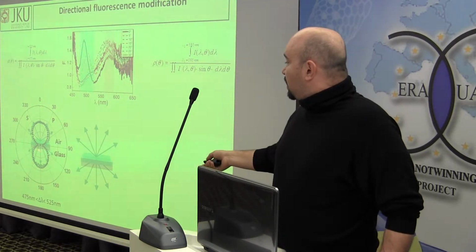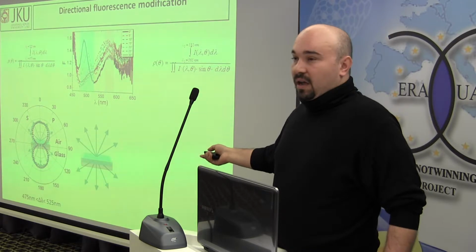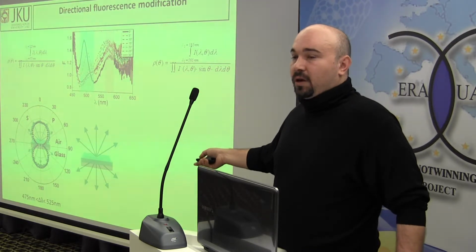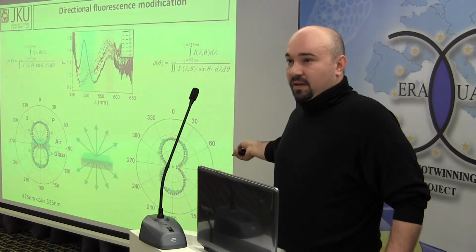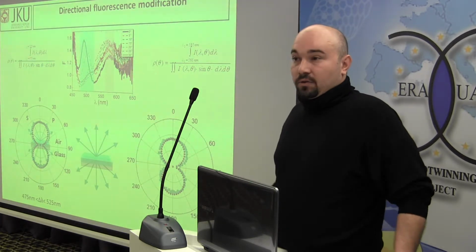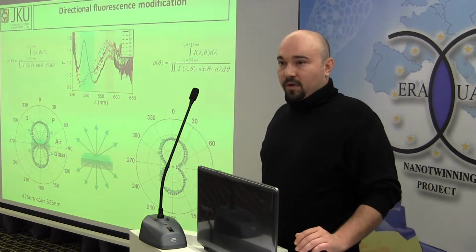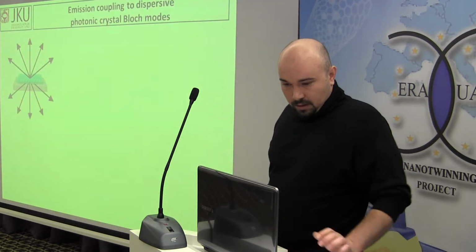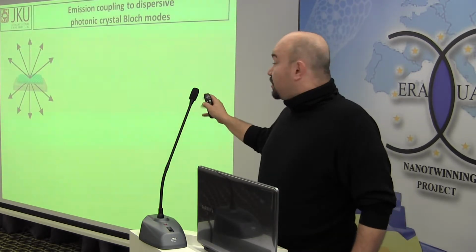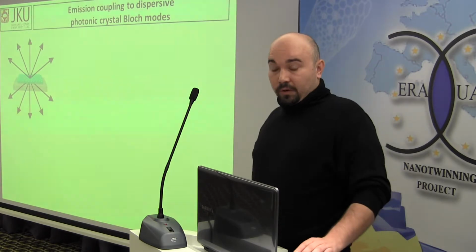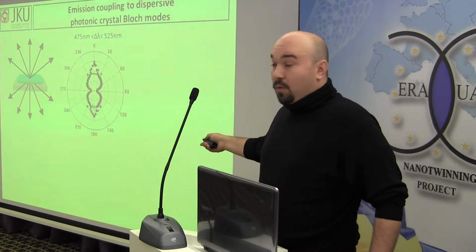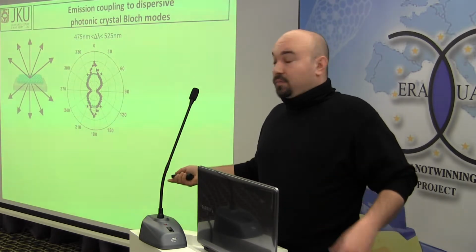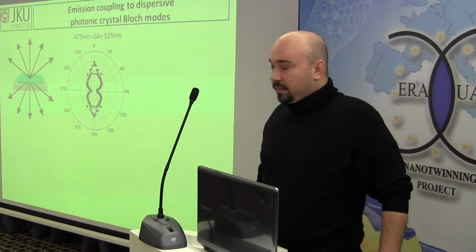And what we see is the green light dots are experimental values, and it's a purely cosine square behavior. And of course, the same for 580, the region of the non-dispersing feature in our former fluorescence spectra. When we take now a closer look at the photonic crystal modes, what we see is that for small angles, we have a deviation from this cosine square behavior.